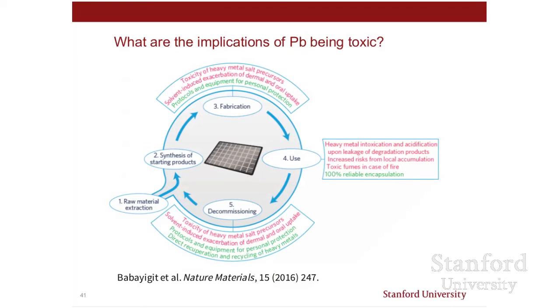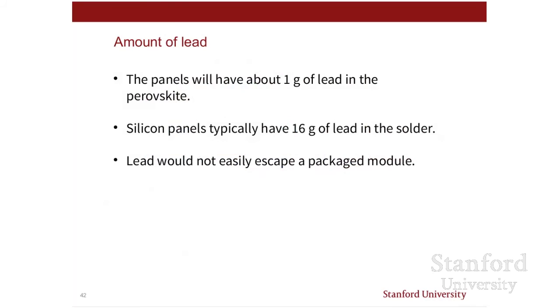There are plenty of industries that use lead and other toxic compounds, and it is possible to protect workers. And when the panels expire and are decommissioned, it will be very important to take the panel apart and properly capture the lead. Something else to think about: these panels are only going to have about 1 gram of lead in the perovskite layer. To put that into perspective, people may not realize this, but today's panels already have 16 grams of lead in the lead solder. So it's a very small amount of lead.